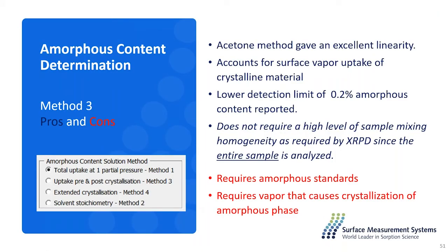For this method, one advantage is that it's a very sensitive method, especially for low concentrations of amorphous content in the material, compared to the traditional method. It can detect amorphous content as low as 0.2%, giving very good reproducibility. And the requirements for this method: we first need to have a standard with no amorphous content, and we also need to find a vapor that will induce the crystallization point.